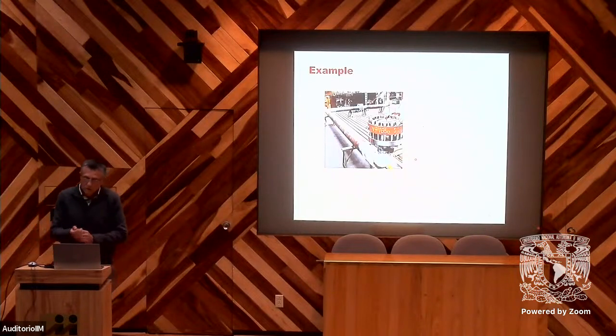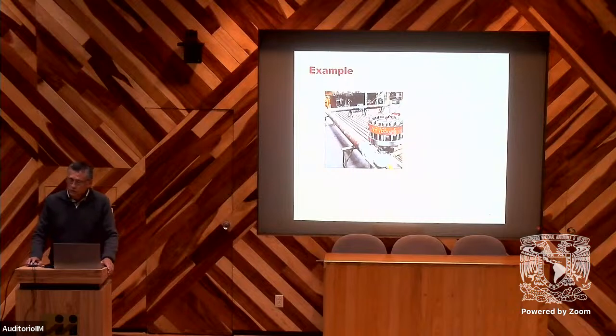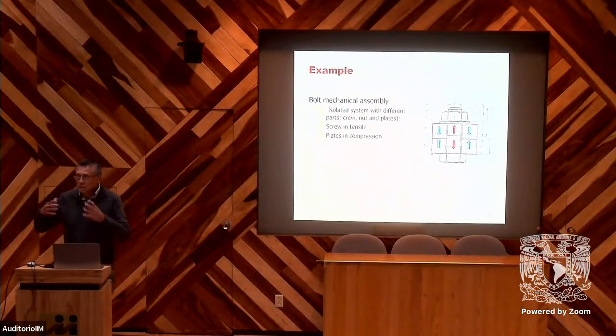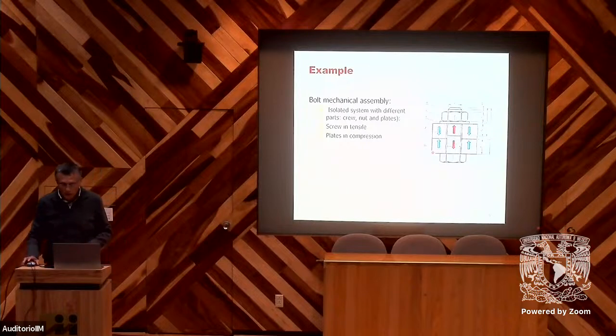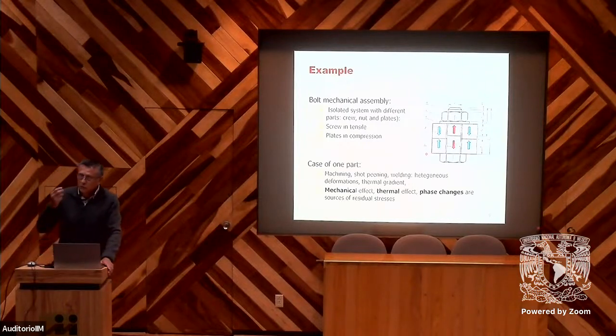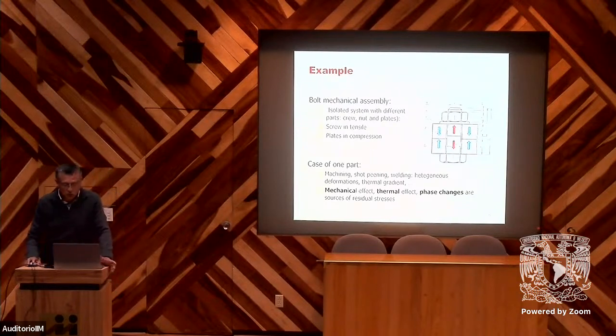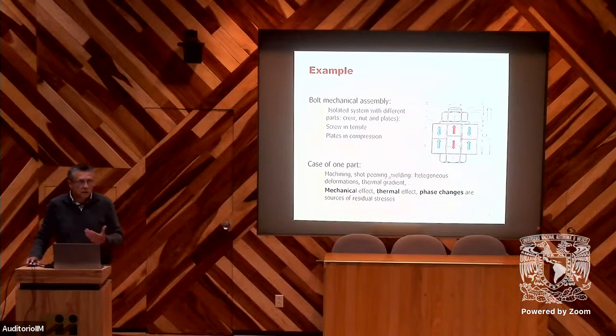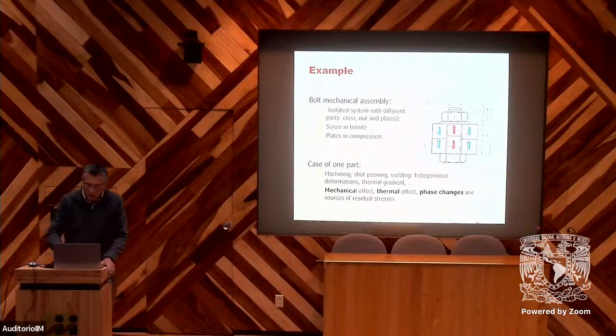To understand the origin of residual stresses, we can start with a very simple example. In an assembly by bolt, we can see that in this assembly, we have some parts in tensile and other parts in compression, and the whole system will be in balance, in equilibrium. So the question is, what about the case of one component? For example, after machining or shot peening, welding, we get heterogeneous deformation or thermal gradient, and this will induce residual stresses. So we will find different effects at the origin of residual stresses: mechanical effect, thermal effect, and phase changes.